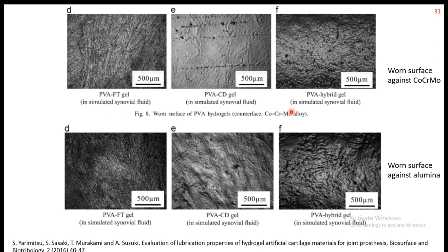Not much work has been done on the wear aspect of hydrogel, but some results show that perhaps PVA FT, or freeze-thaw process, gives a better result with less wear compared to PVA CD. This needs to be properly evaluated in vitro in our pin-on-disc machine or multi-directional pin-on-disc machine, so that we can understand how the PVA gel will perform in an actual system.